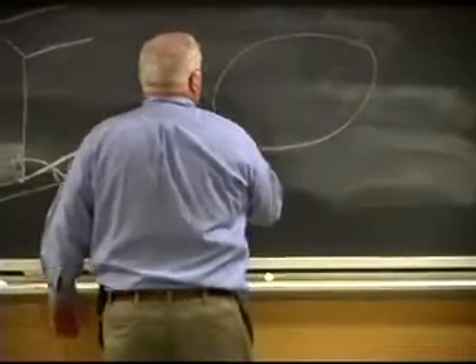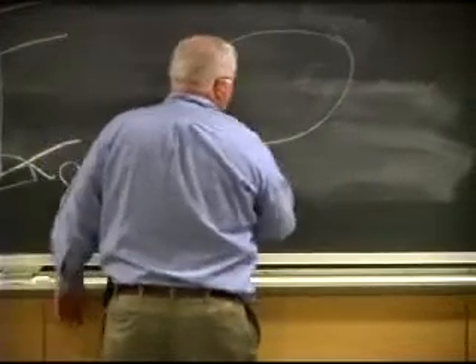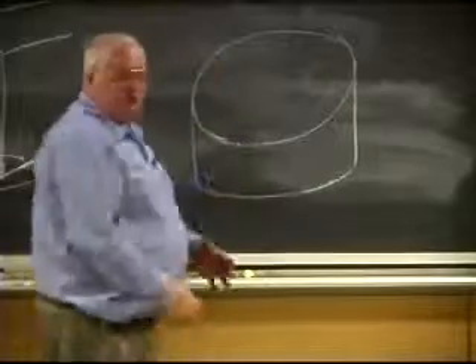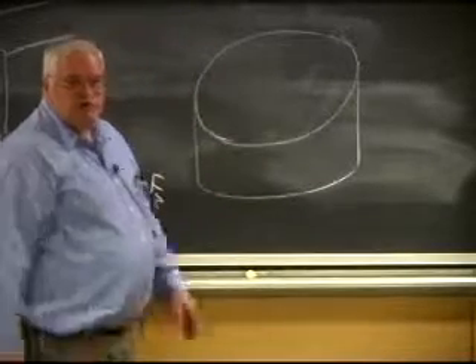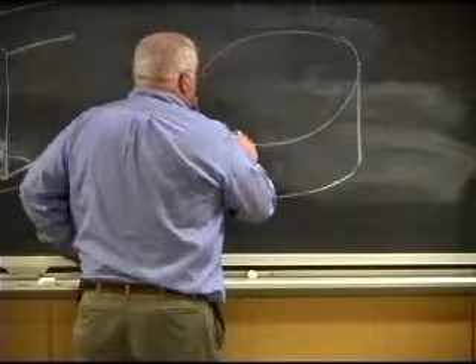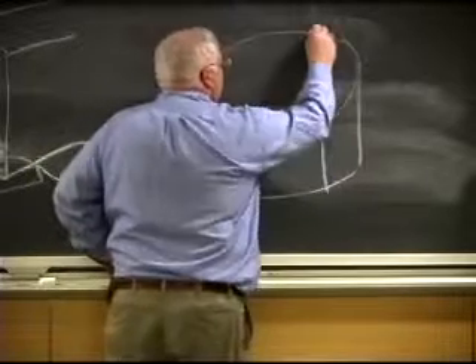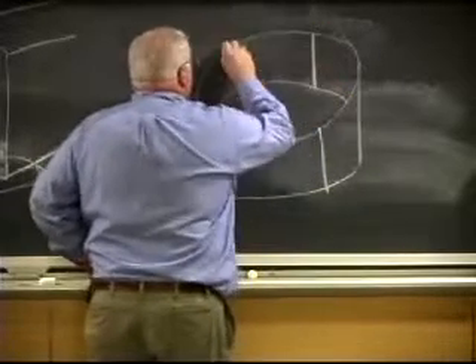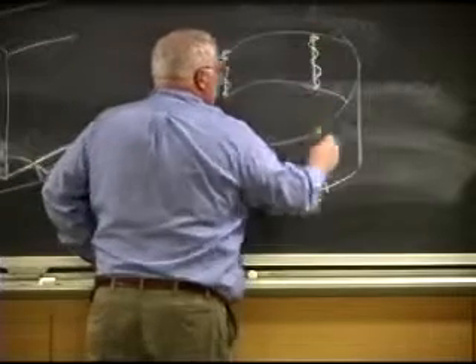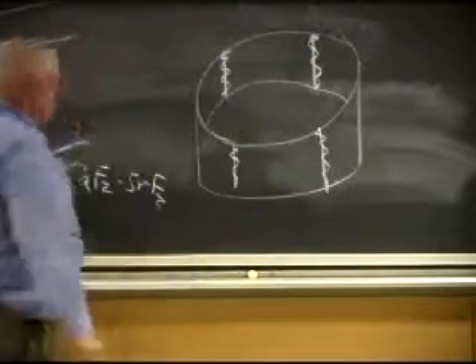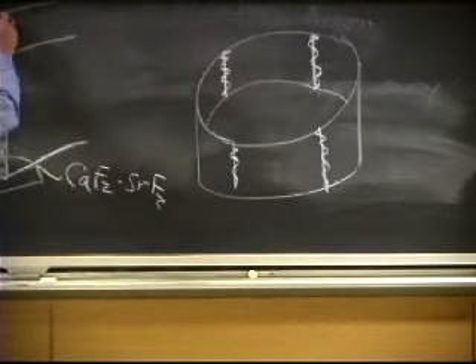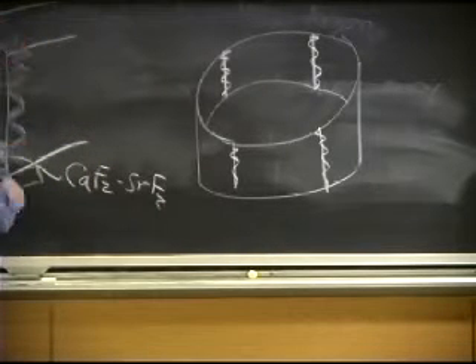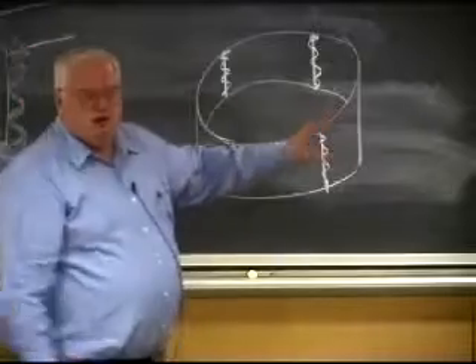In fact, someone asked me yesterday, or actually I don't know if they asked me why, but I told them at Electric Boat, when you're making the cylinders for the 30-foot diameter cylinder for the hull, they actually put in about 4 vertical welds. So they do vertical up welding, which is like electro slag. They don't do electro slag because the problem with electro slag, with the speed of this process, you get heat affected zones in this. They can be an inch thick, okay?